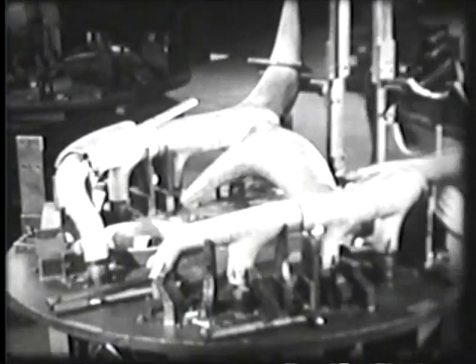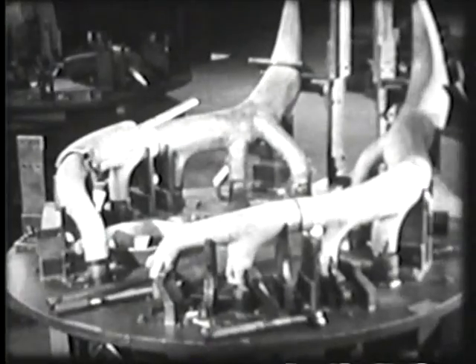Even such a seemingly unimportant item as an exhaust stack requires special equipment. These drop hammers using zinc dies form sections of exhaust stack from stainless steel sheets. When the sections have been welded together, they are assembled in a jig to form a completed collector ring. Hydraulic presses with pressures as high as 2,500 tons are employed to draw the aluminum alloy into the many forms required. Each piece to be produced presents its own problem in the matter of dies for use on the press equipment. A tool design department is a necessary adjunct in this specialized production industry where parts are counted in hundreds and unit costs must be held to a minimum.